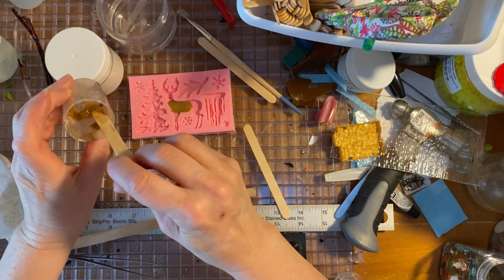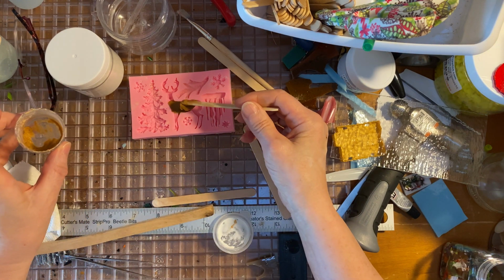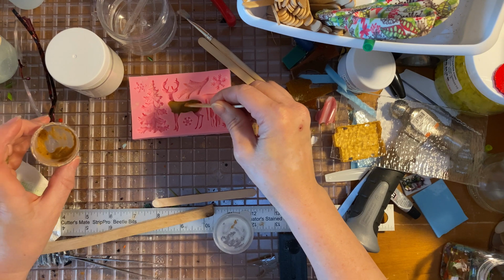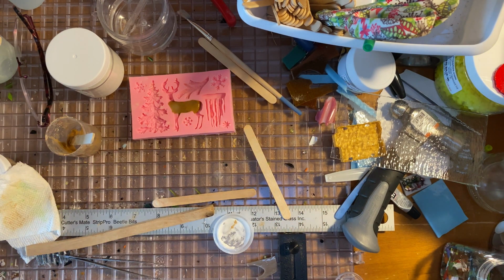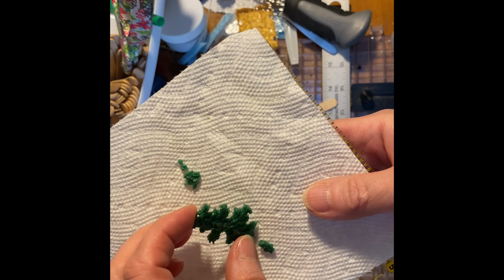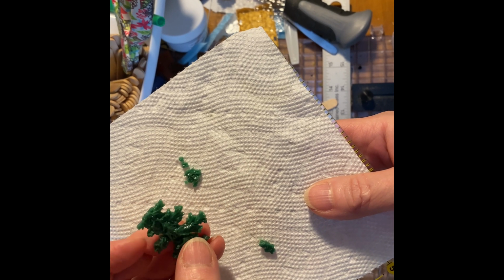If you don't do that, you're going to end up with a lot of air bubbles and the piece is going to fail. And I can show you one out of the kiln that failed because I didn't put enough glass powder in the slurry. This tree just didn't have enough. It had enough in this base part. Well, actually it didn't have enough there either.